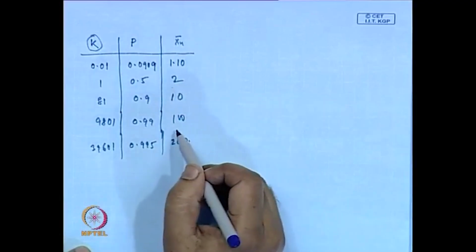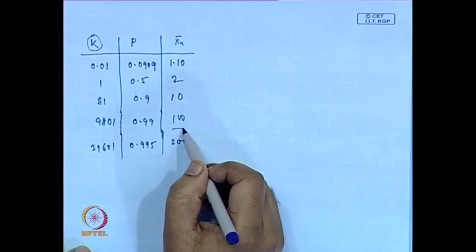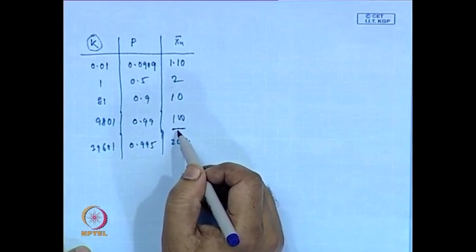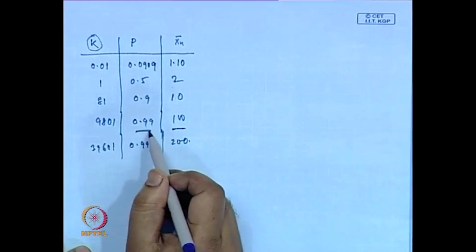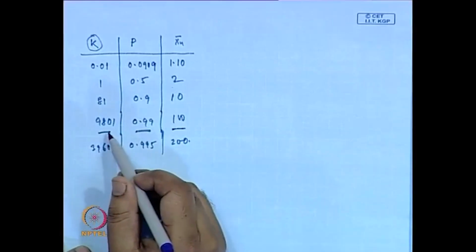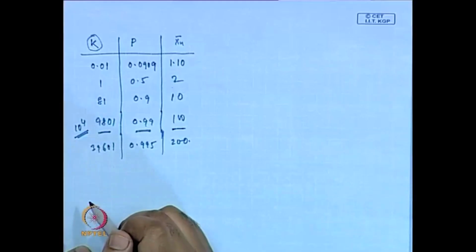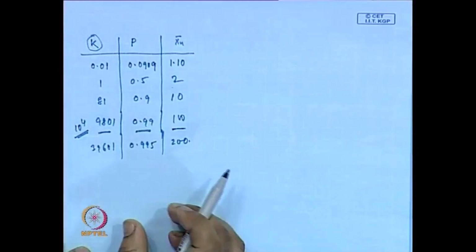If you want to build molecular weight, say a degree of polymerization of 100 in a closed system, then your equilibrium conversion has to be 0.99, which means your K has to be almost of the order of 10 to the power 4. That means the reaction has to be very highly reactive, so that by itself, without removing the byproduct, you can get the product.